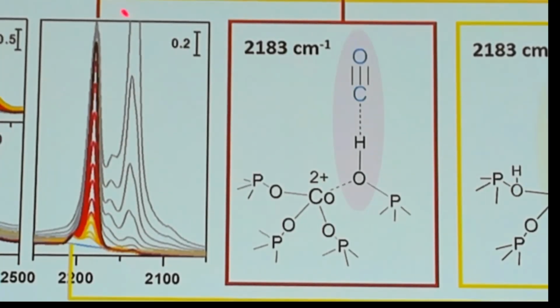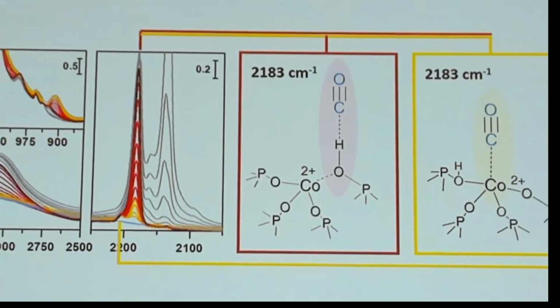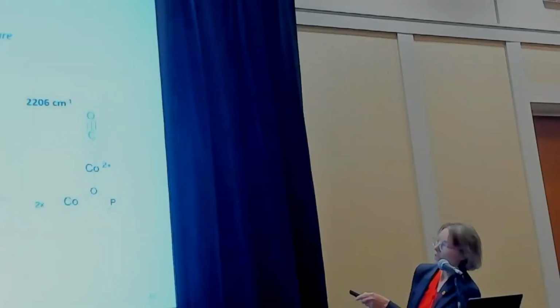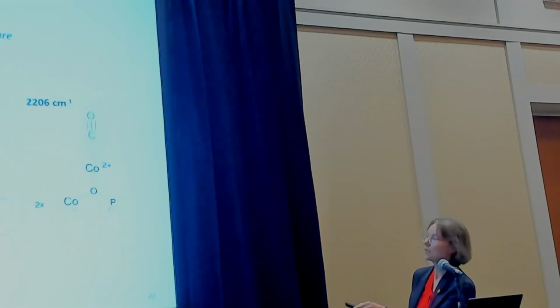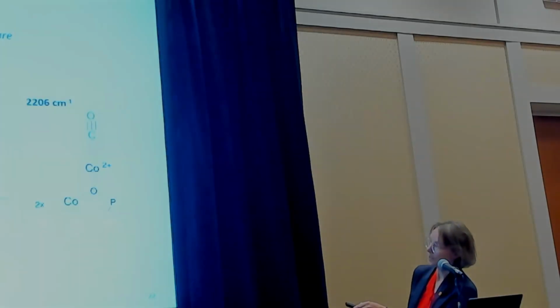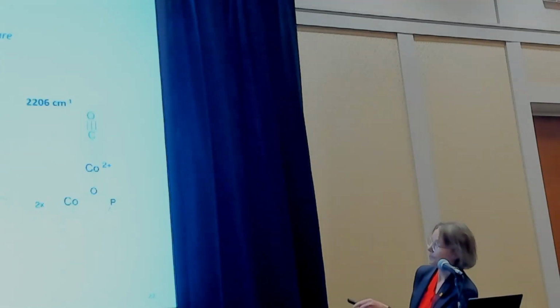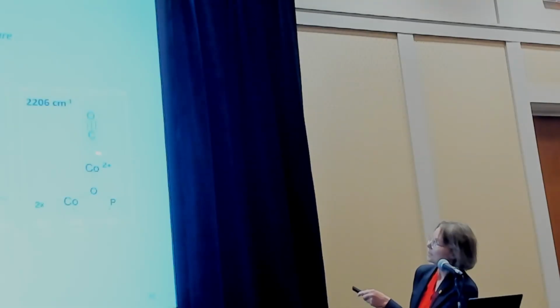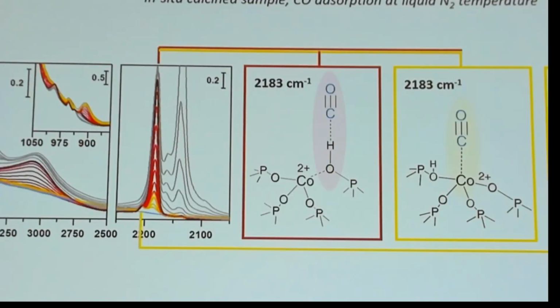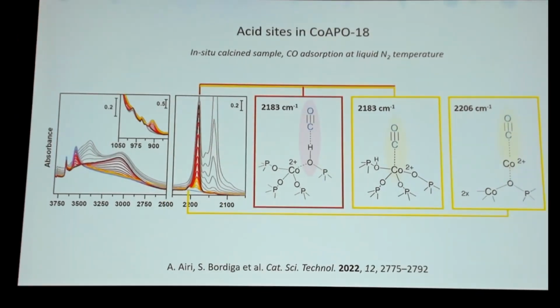And this 2,183 reciprocal centimeter peak is typically due to the adsorption of CO on the Brønsted acid site. But since we saw this very persistent part here, it means that there must be another site that is also giving the same signal. And this was allocated to CO adsorbed on the cobalt, which is part of the structure. So it's actually cobalt as a Lewis site which is present here. And then we have another site, and that is CO that is ion exchanged onto the Brønsted acid site, replacing the proton in the structure, and CO is adsorbed on that, and that has been seen also in other contributions.